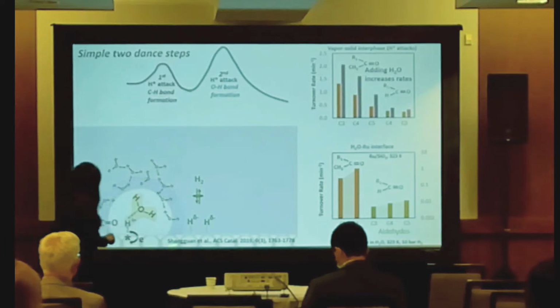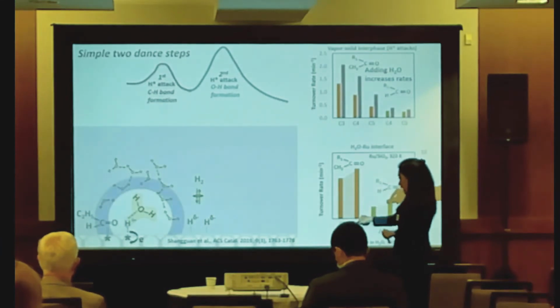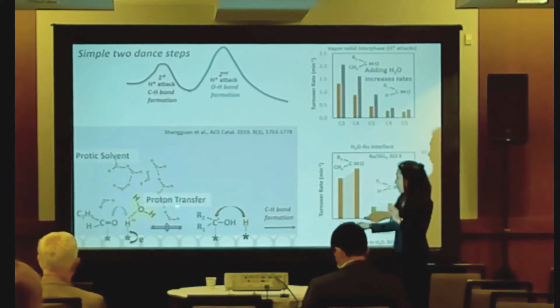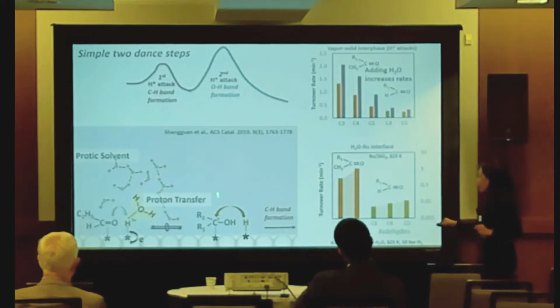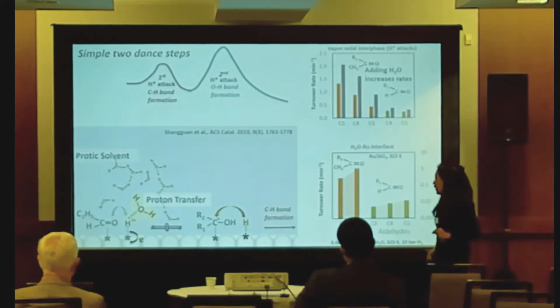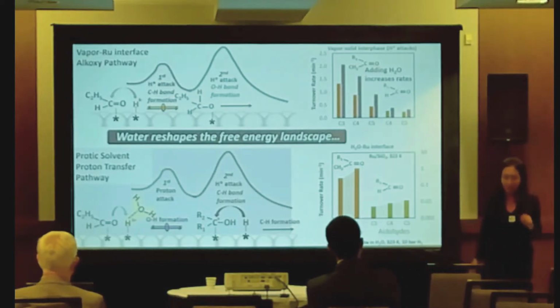And this part is related to the incipient formation of an interfacial proton. Hydrogen now donates electron into the metal d band and is ready to do the chemistry. The first step is proton transfer, attacking the oxygen. The second step is now the CH bond formation that completes the catalytic cycle of two steps.